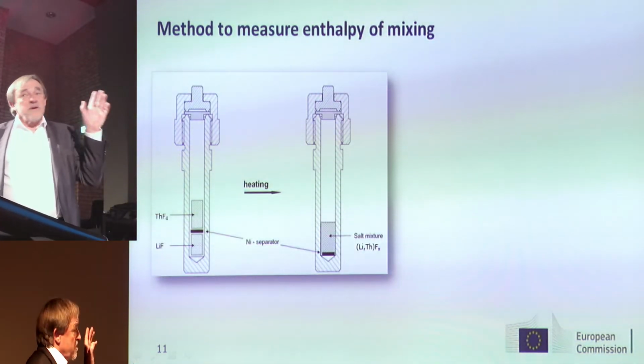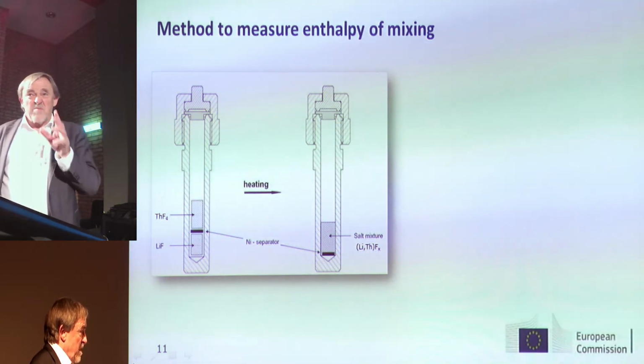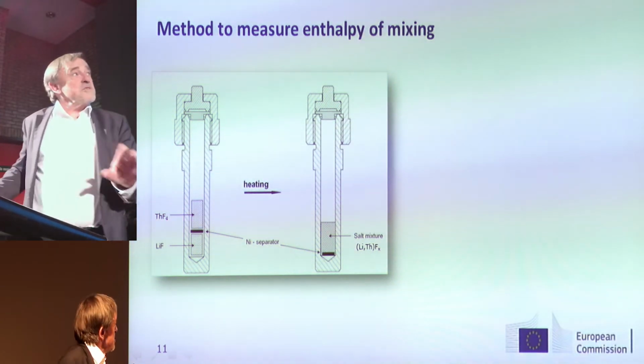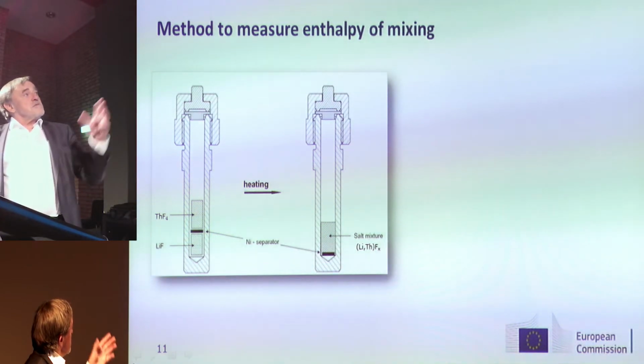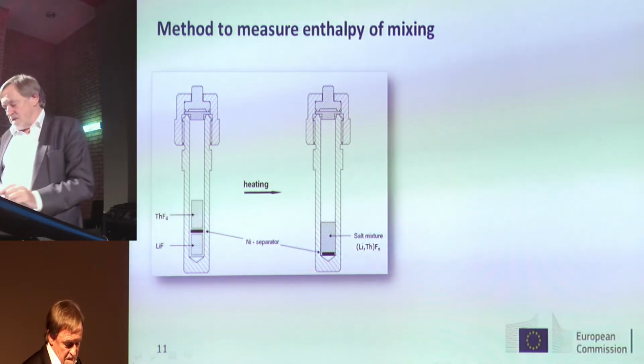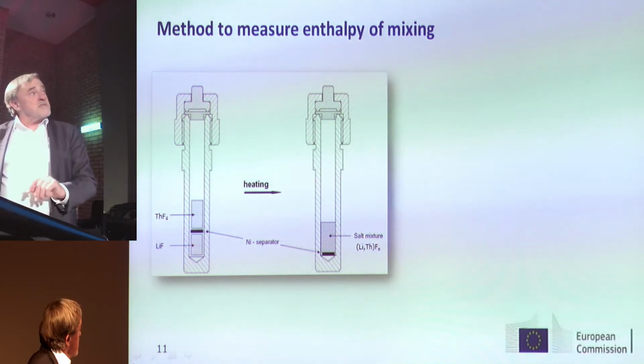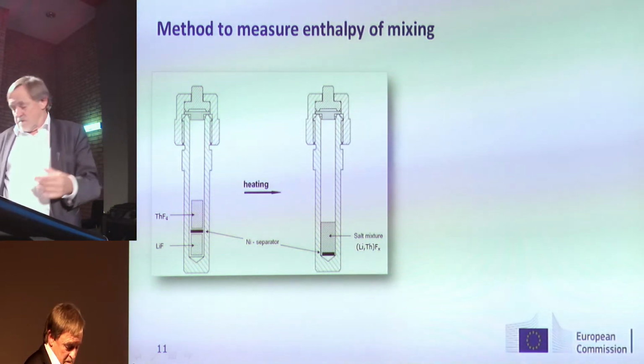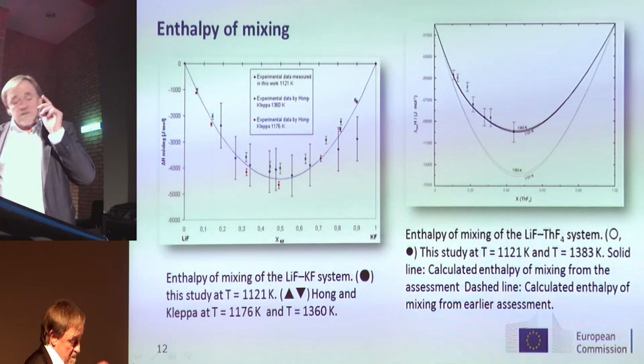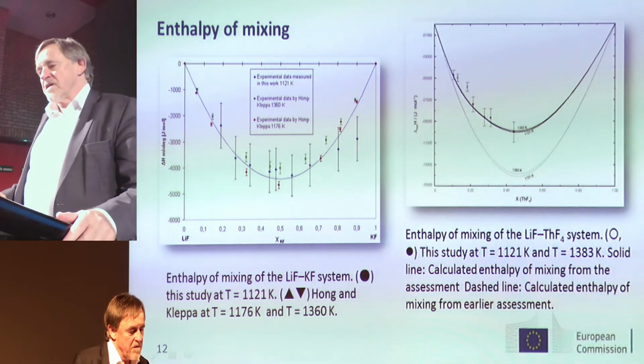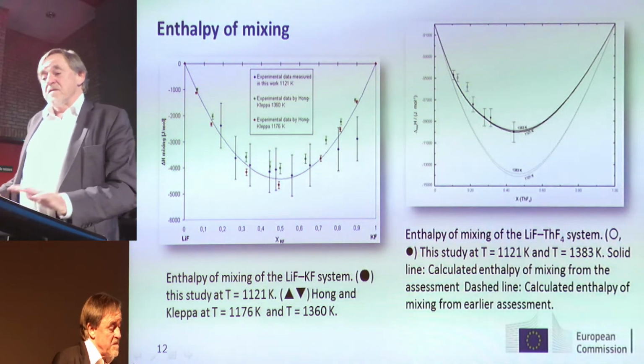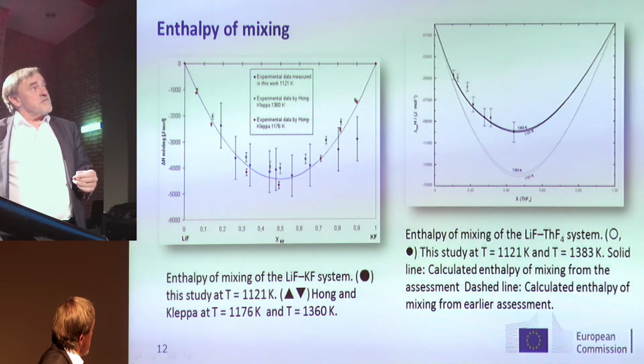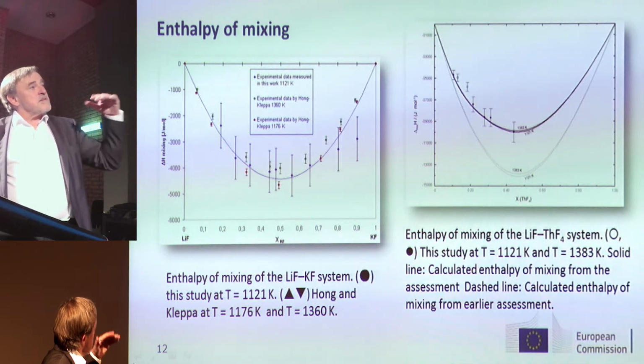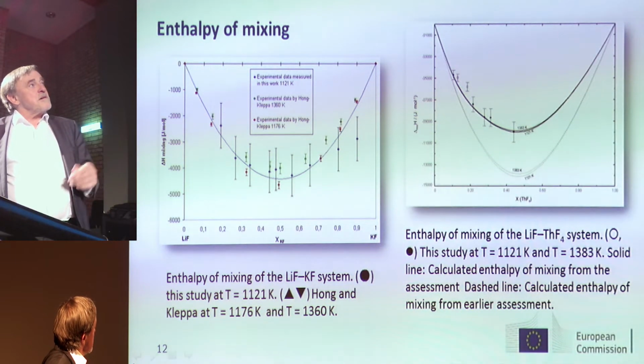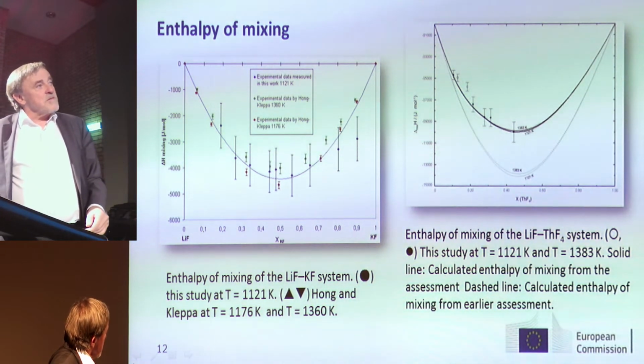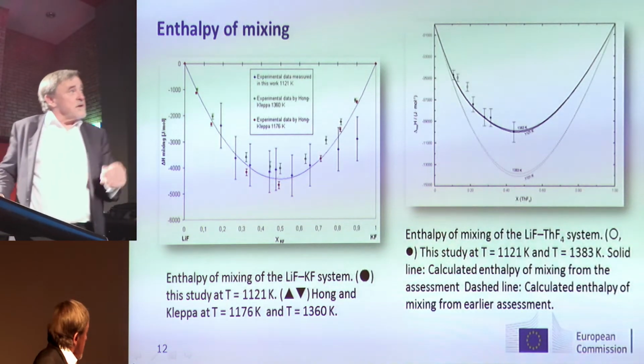Then this I might skip because it has been explained very well by Anna Smith this morning. So this is the mixing enthalpy. So this is this mixing phase of these two phases which are mixed with this nickel separator, and this curve, which has been explained this morning also very well by Anna Smith, gives this result as they are shown on this view graph. So you see here in the first case for the verification, we have measured the enthalpy of mixing of lithium fluoride, potassium fluoride.